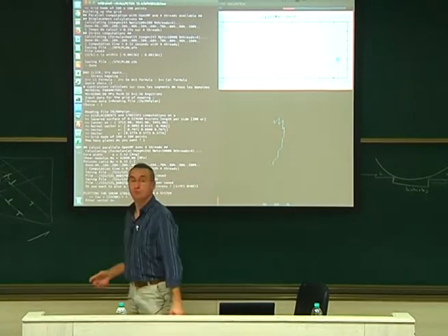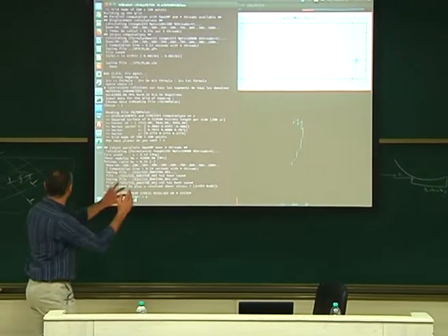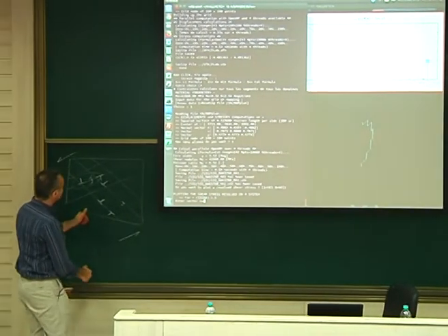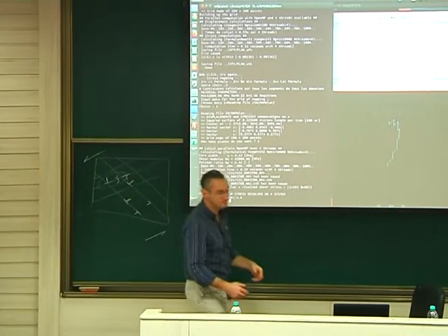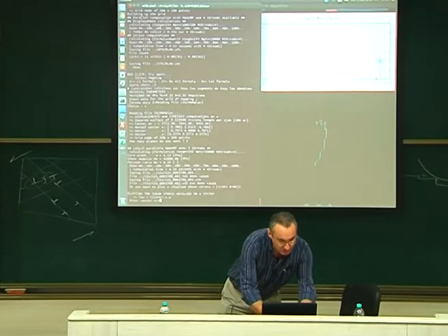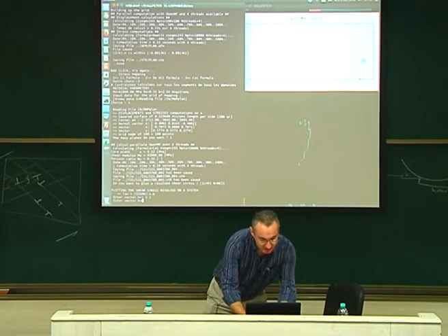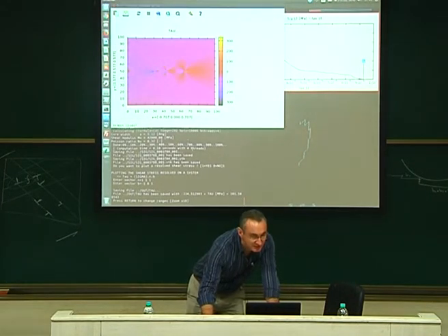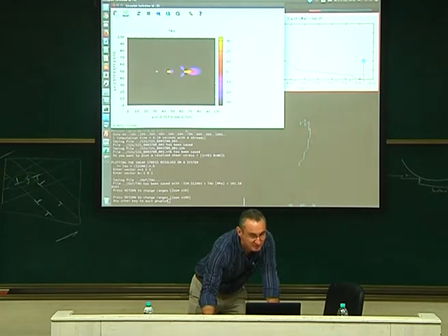So you can compute, for example, a shear component of the stress. So here you have a stress tensor. I will say, okay, I want sigma n b. N is the normal to the plane, and b is bar 101. So n is 1, 1, 1. B is bar 1, 0, 1. And this is my stress tensor. Okay, here. And if I zoom a little bit, you see my stress tensor like that.